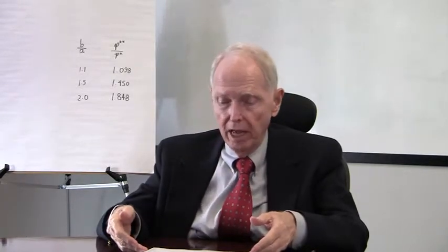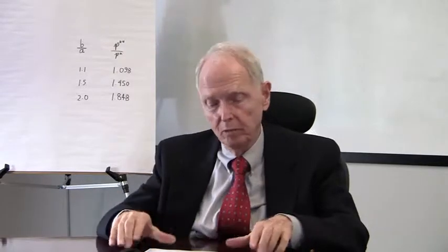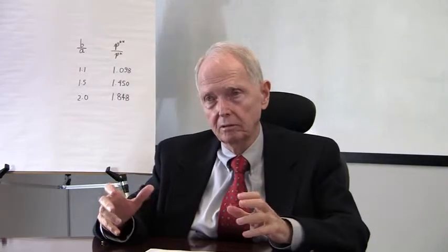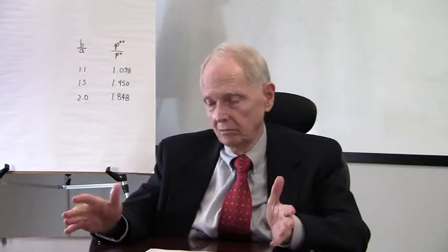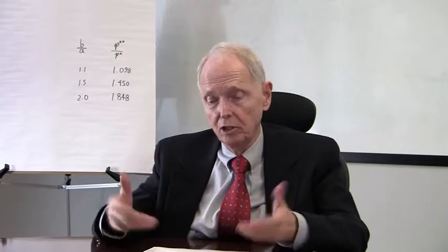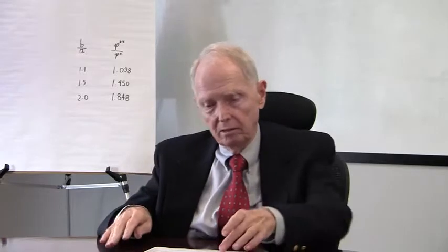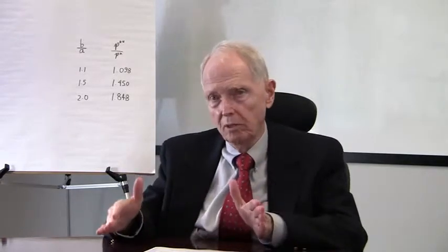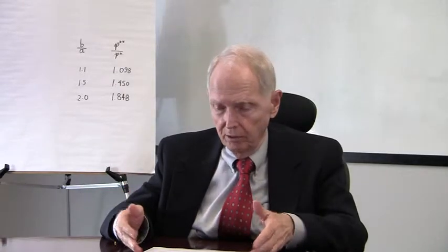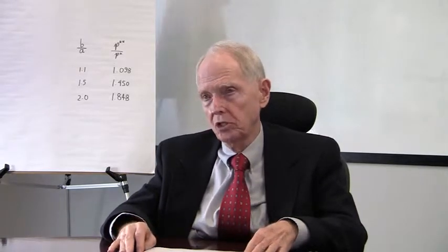But if you were to run that experiment, and if it was a perfectly plastic material and followed the rules we're looking at here, the ratio of the initial yielding to whenever the thing finally broke apart would be roughly the ratio of the volume under the cone to the volume under the parabolic dome that's got a slope on the edge equal to K. So I've got that worked out here. And that turns out to be 4/3.